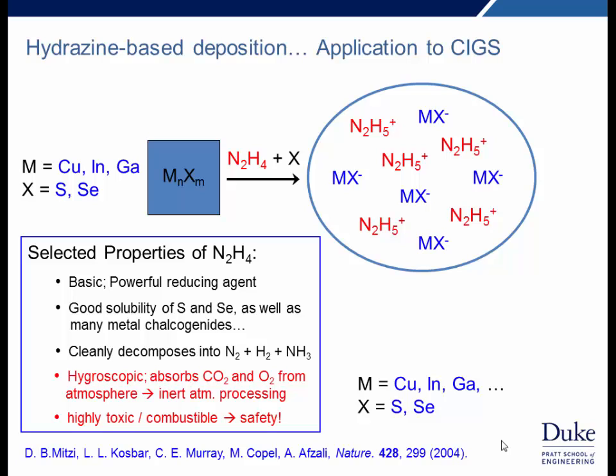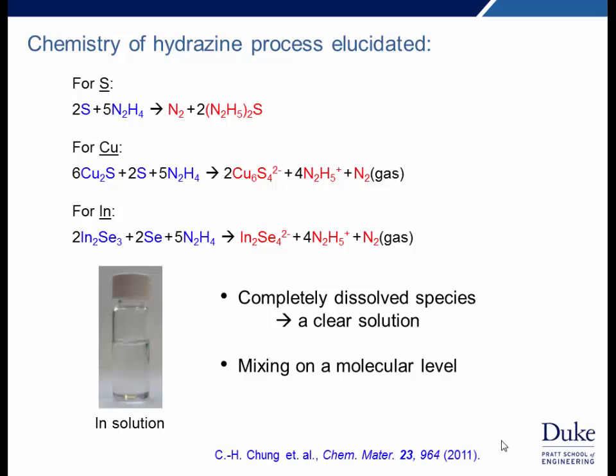But the process is very simple. We just take the starting metals and chalcogens, and dissolve them in hydrazine with excess chalcogen. We create this pure solution, and you can see an example of an indium solution here. Basically, the metals react in hydrazine to form these metal chalcogenide anions and hydrazinium cations, and the solutions bubble, so they give off nitrogen gas.